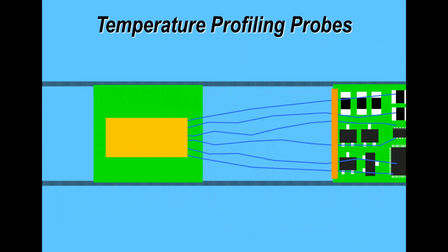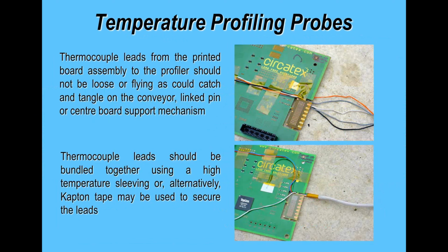Also, it's a good idea to hold the thermocouples on the printed circuit board, but I would suggest not to have the wires loose, as you see in this particular example, because they can catch on parts of the oven or on the conveyor process and possibly rip the wires either off of your board or out of your profiler. So try to hold the wires together. You can use Kapton tape to bunch the wires together, or in the particular example on the bottom here, I show some high temperature sleeving which has been used just to hold the wires together. It looks neater and you're less likely to damage your profiling board.